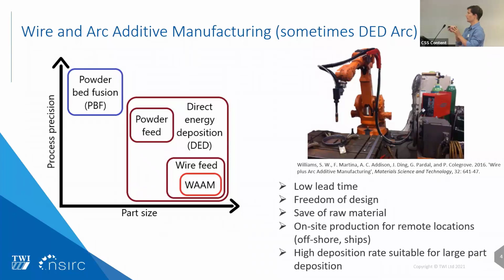As you can see on the diagram on the left-hand side, WAAM is situated here, which means that to achieve high deposition rates and deposit large parts, it costs the precision of the process. You'll have poorer precision compared to other additive manufacturing processes, especially powder-based ones. So WAAM really shines and is relevant when you deposit large metallic structures. To give you an idea, a typical layer for steel would be around 1 millimeter, which shows how imprecise this technology can be.